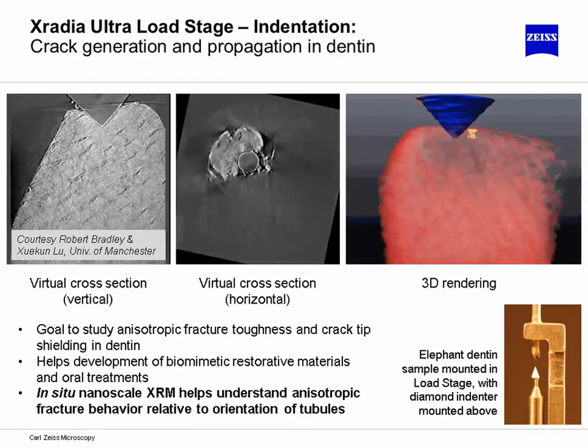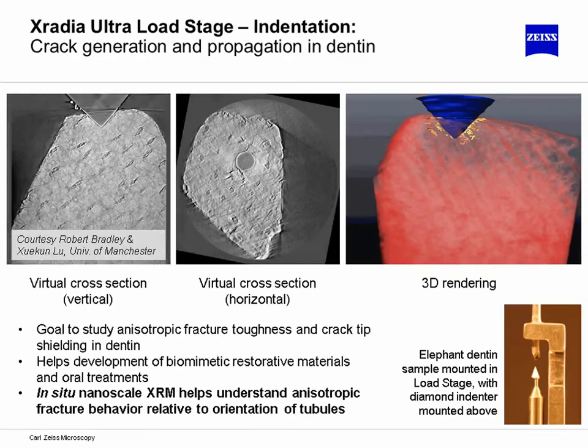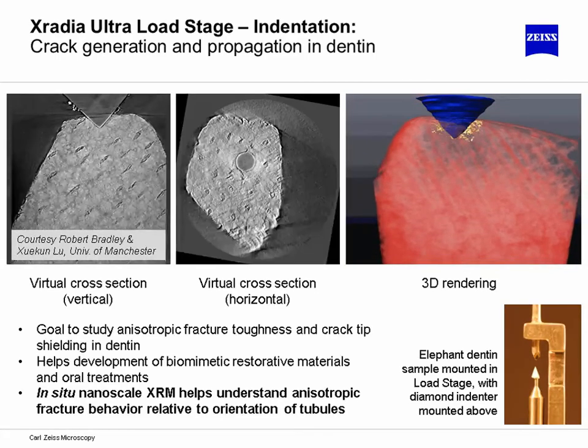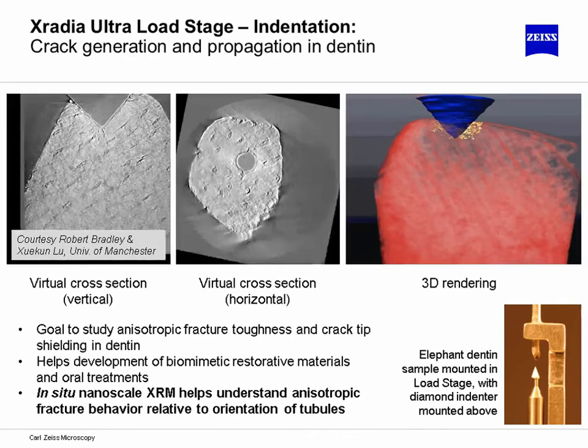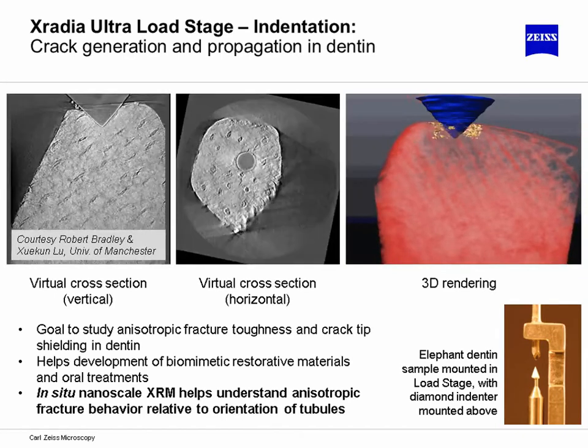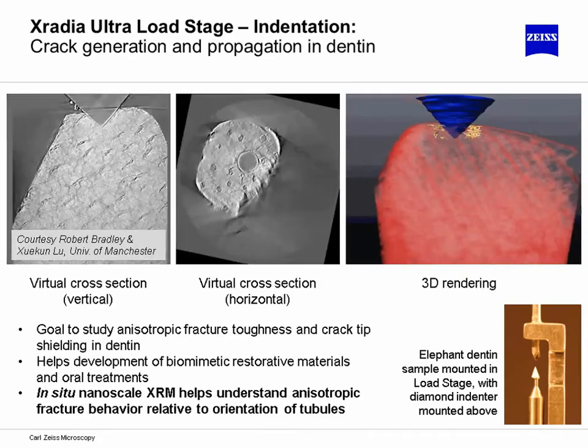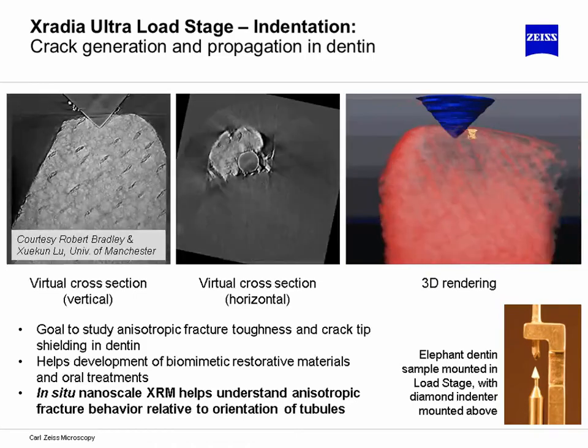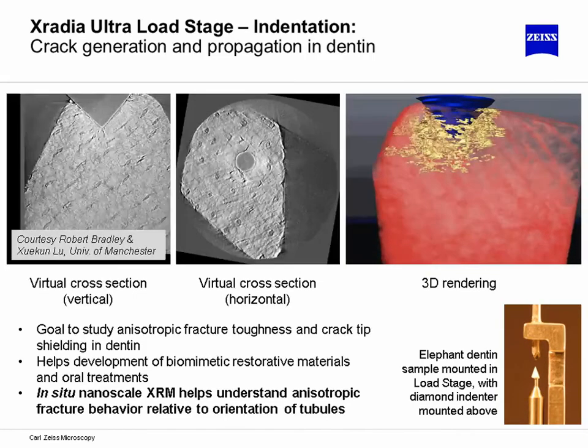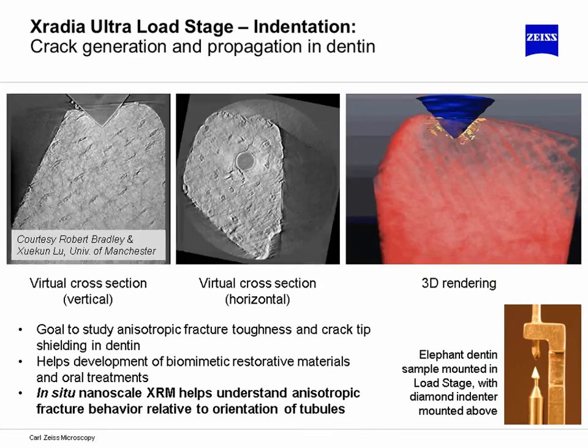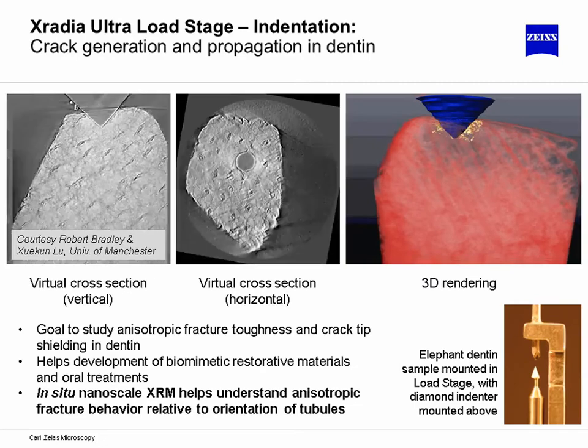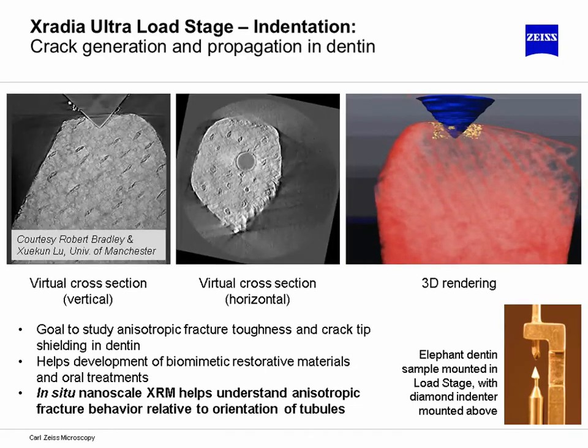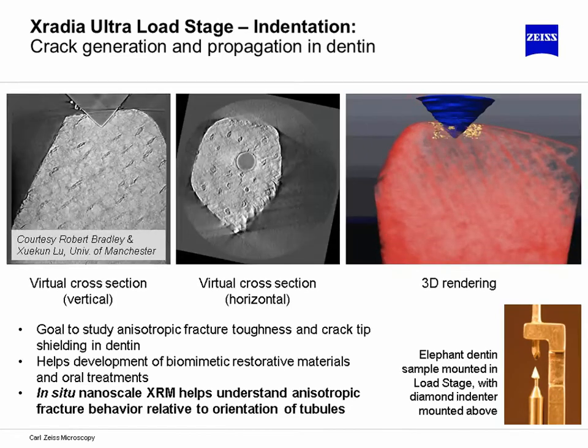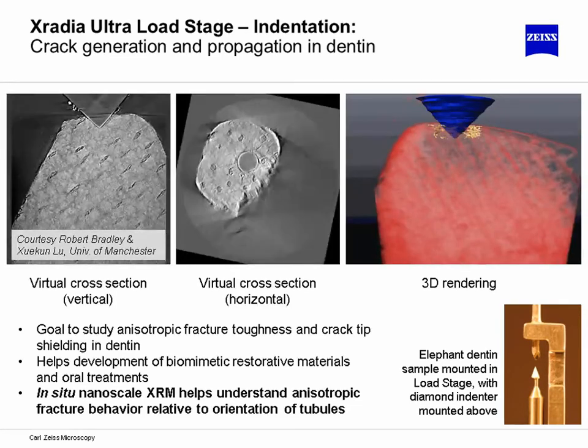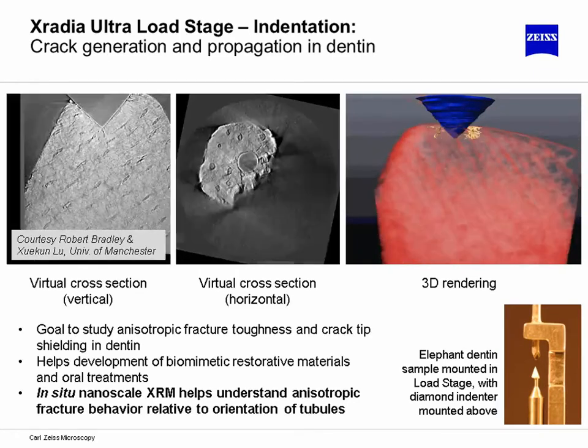And my final slide on the Ultra is really highlighting some of the future directions, something that a number of groups are very active in now. Some of the very first results from last year are showing some indentation done on dentin, and this dentin material is now being indented or compressed. This is a sharp diamond indenter tip, and we're looking at the crack propagation in this natural composite material, where you see some of the dentin tubules running down through on the left here. These are a few different views in the segmented volume on the upper right-hand side. So this helps in our understanding of how cracks propagate. These are multiple different three-dimensional tomography acquisitions at the nanoscale over time. This field of view here is 65 microns across.